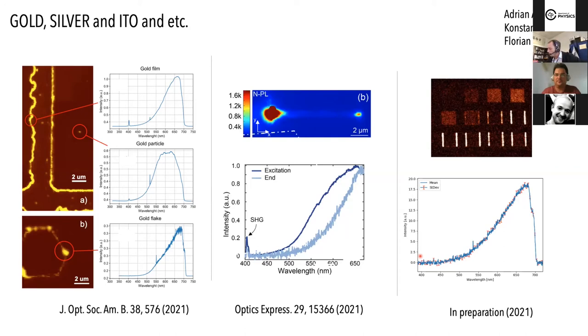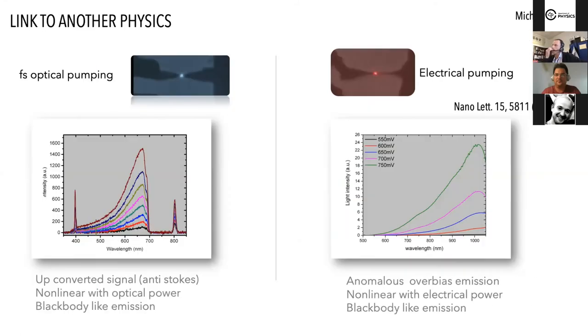Okay, and to answer Jonathan's comment, we also made the link to another physics. What I'm showing you here is a comparison between an optically pumped system on the right-hand side, and on the left-hand side, this is what we've been talking about for the last half an hour, and electrical pumping of a device with very similar characteristics. So here is an optical image. We focus the light beam here and we record the nonlinear photoluminescence. In this image here, we inject electrons in a very small gap. I don't want to go too much into the details, but we also record light coming from this electron injection device.